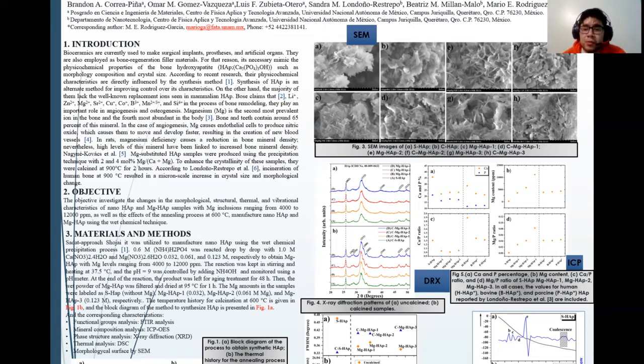ICDD card number 00-009-0432 for hydroxyapatite. The peak located at 25.879 corresponding to the 002 plane is slightly shifted to the right, indicating a reduction of the lattice parameters. This shift indicates inclusion of magnesium in calcium sites because of charge balancing. The decrease in the lattice size is due to the smaller atomic radius of magnesium than that of calcium.